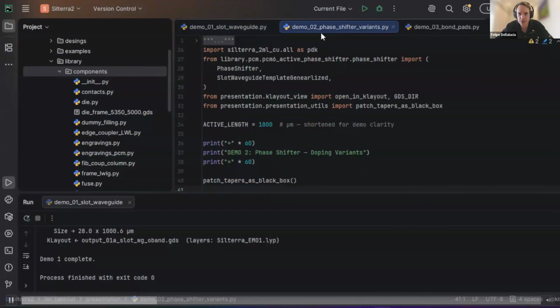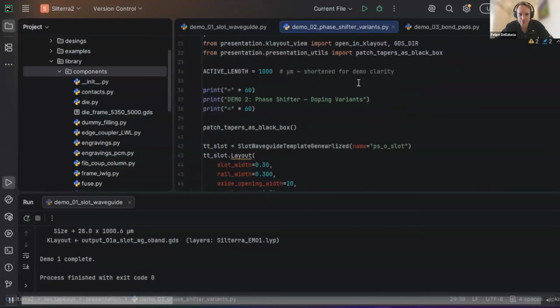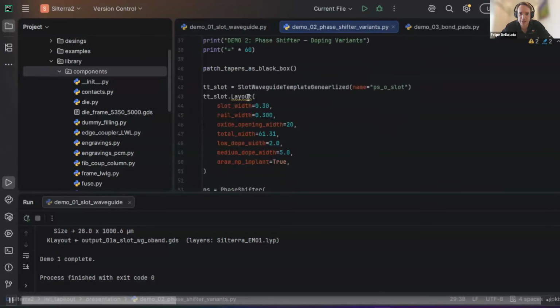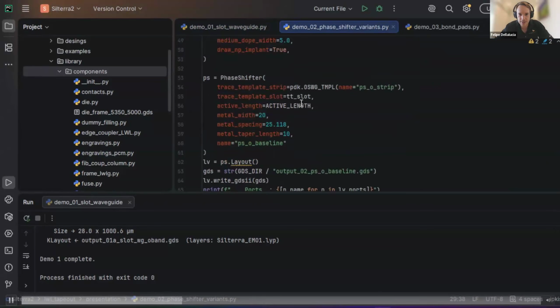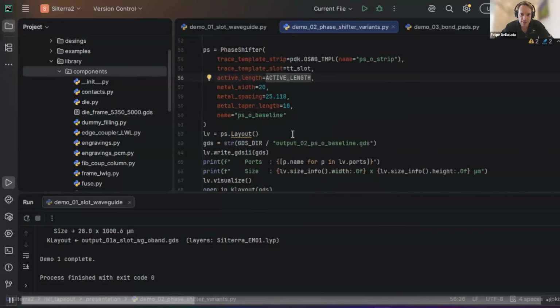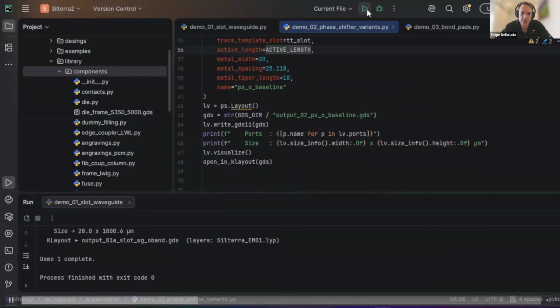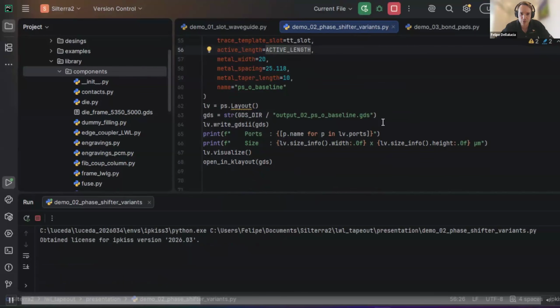From that, you can start increasing the hierarchy, such as making a phase shifter. So the same way that we did before, we just import the SilTerra PDK and the phase shifter component from our library. And you can set the active length the same way that we did before. We instantiate the cross section in the phase shifter. We use the same cross section that we used before, that I'm showing here, the active length. And it's also parameterized the metal width that we're going to use in the electrodes and the taper of the metals that we're using.